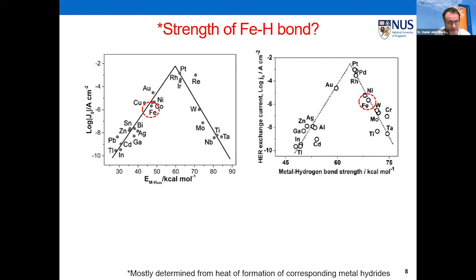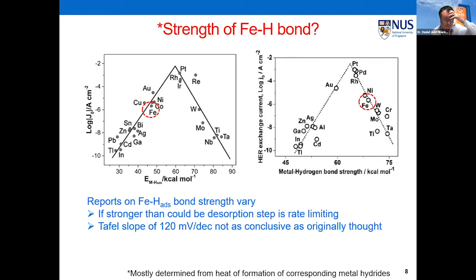So I used to think that the fact that it was 120 millivolts meant that the adsorption step was rate limiting, and so it wouldn't matter whether the bacteria removed hydrogen from the surface. However, that argument is not as strong as it used to be. But it's not the only argument against cathodic depolarization.